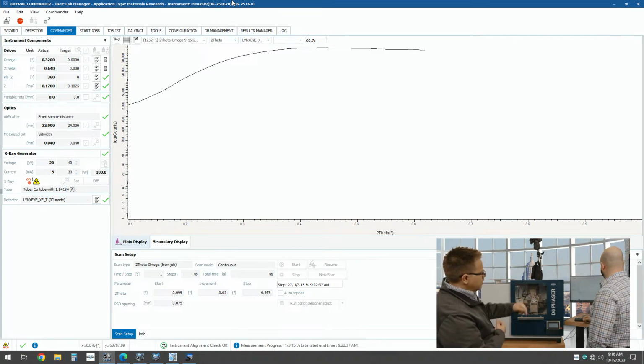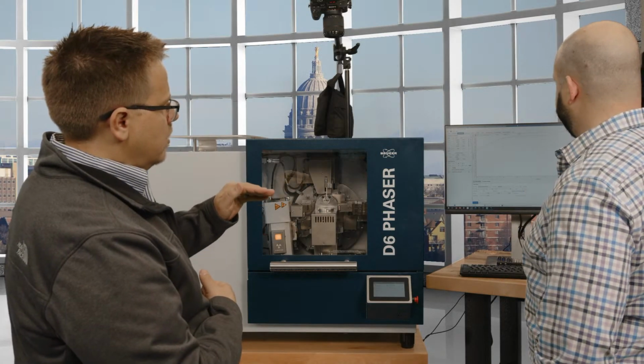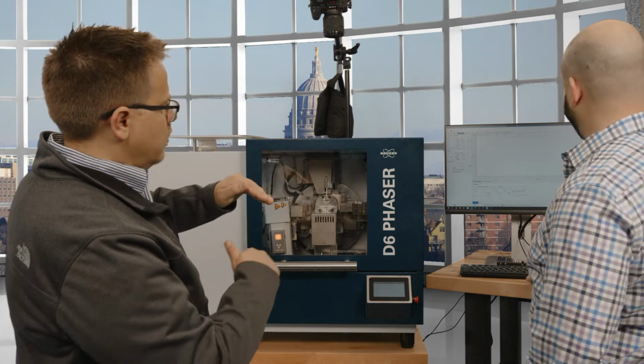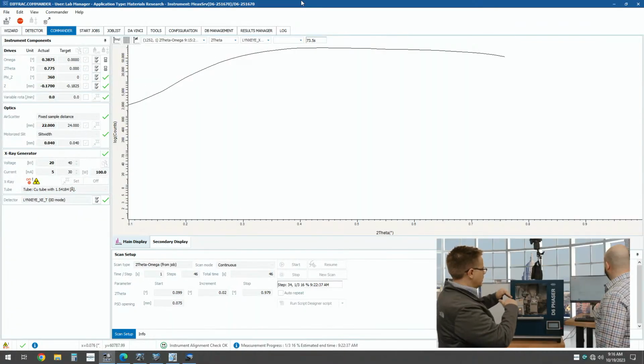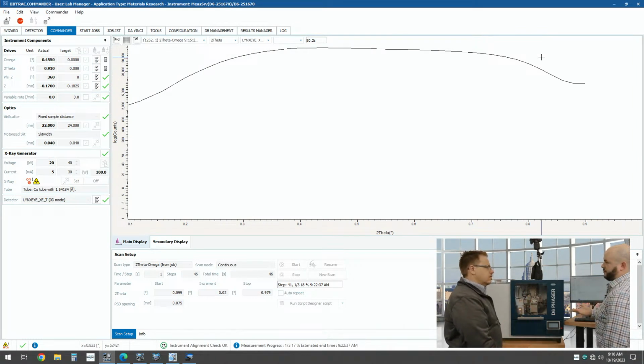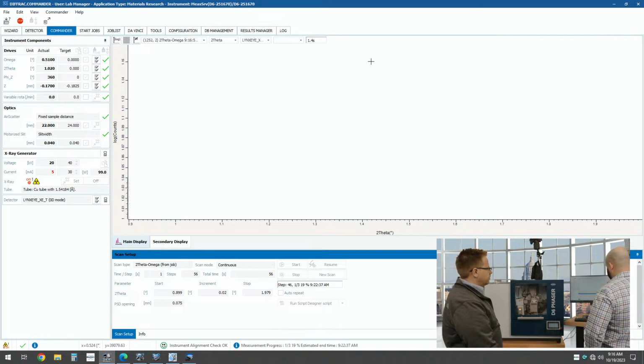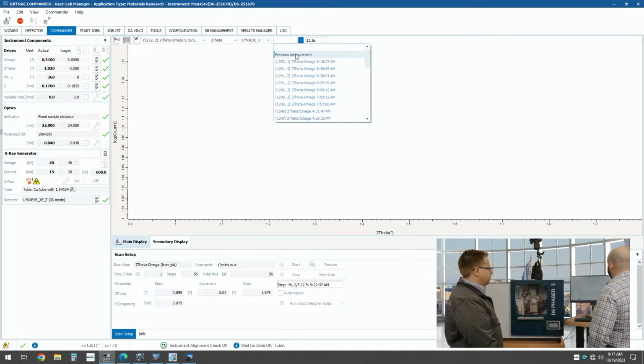Yep. And then here in the scan, we see that the beam is, as it goes up, starting to fill the whole sample, the plateau, because it's reflecting off the whole sample surface, and now we get this critical edge right here, which is basically determined by the density of the top surface of the sample. All right. And then we start to see these fringes. That's right. So you can see that's our first segment. Now it's going to ramp the voltage and current up for the second segment. So here we're ramping up to 600 watts now. And I can go ahead and overlay the previous measurement.